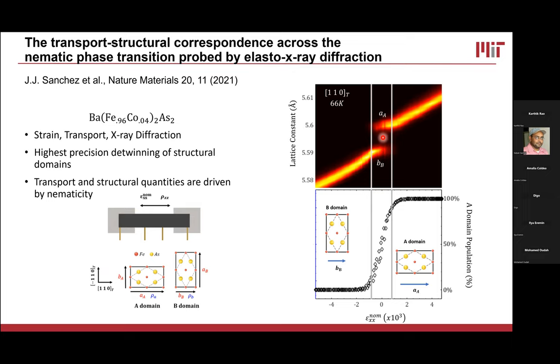And those two peaks correspond to a longer lattice constant and a shorter lattice constant, which correspond to this longer and this shorter lattice constant here. Now, when I apply tension, what happens is I promote the A domain and I switch the system smoothly into mostly A. So I can characterize that by this black line here, where each one of these data points is a single X-ray scan that's been analyzed to give me the ratio between the A and the B domains.